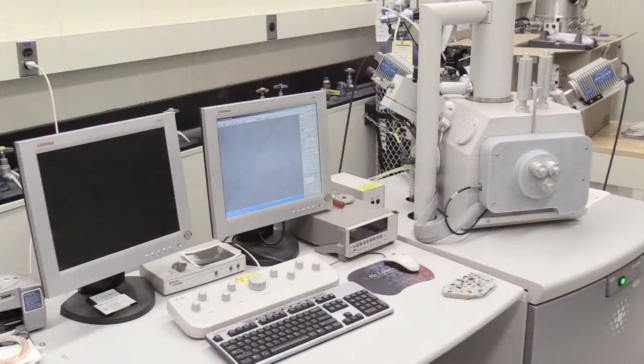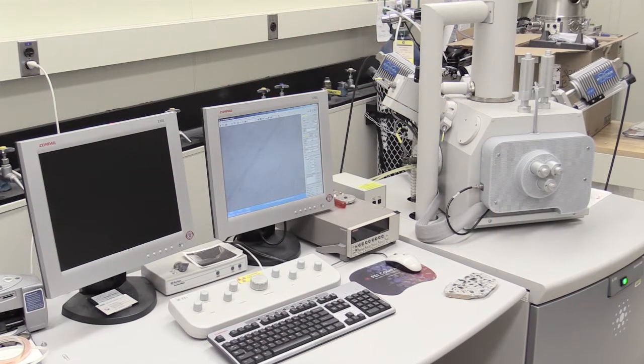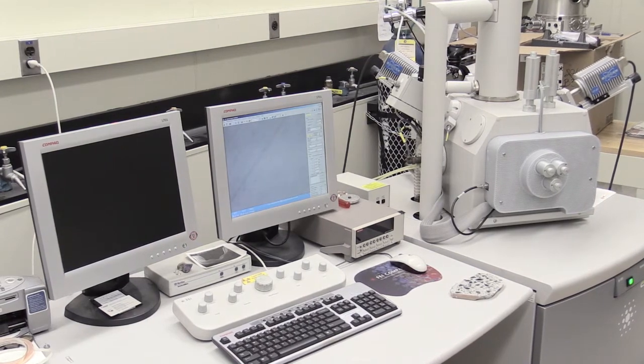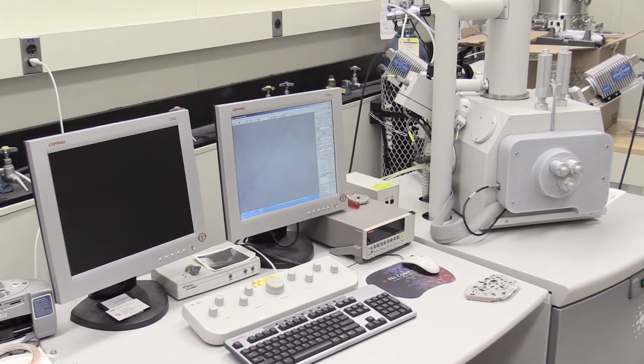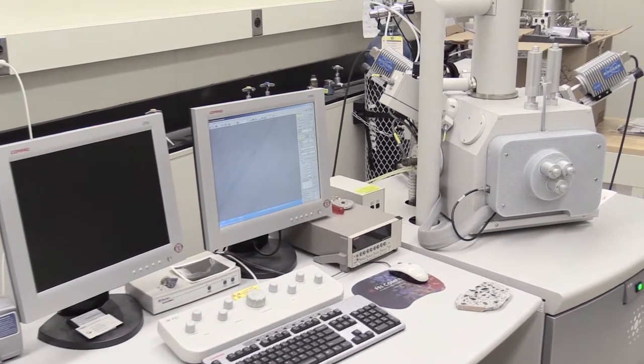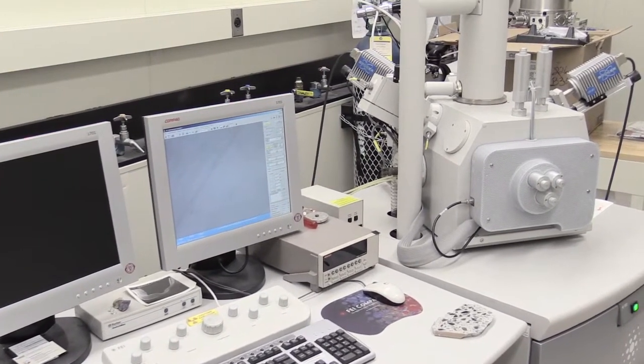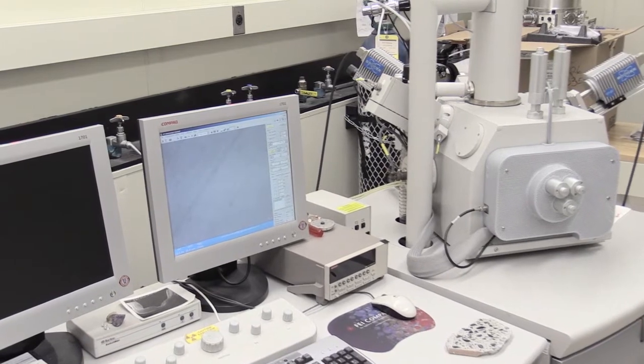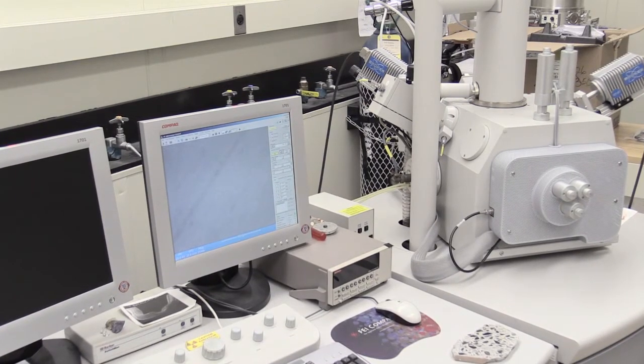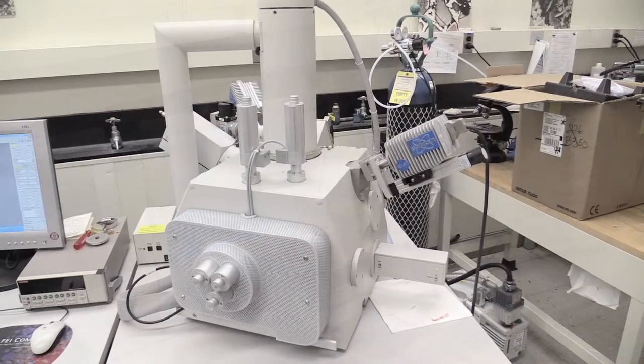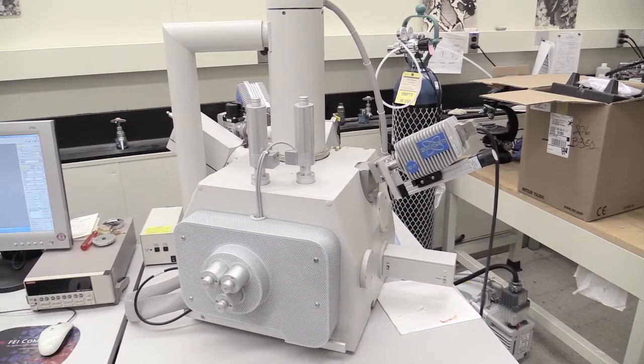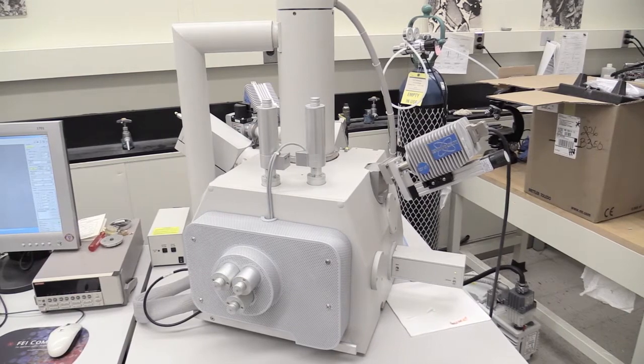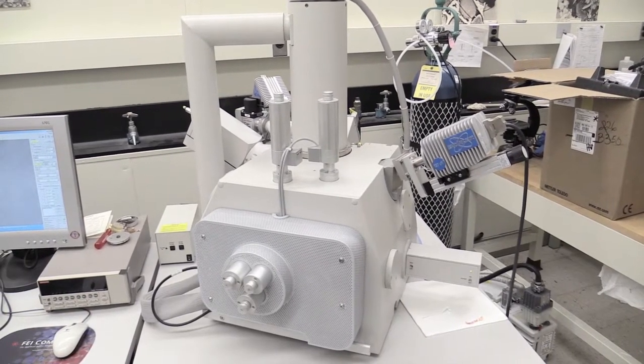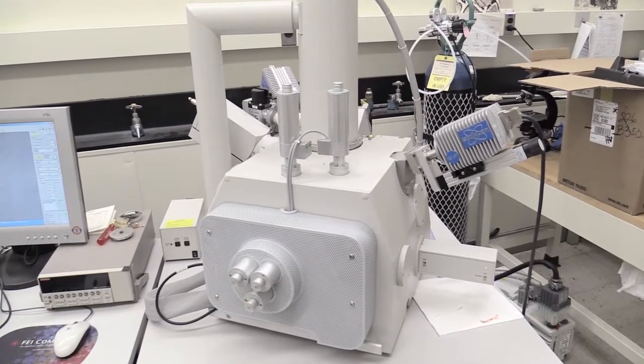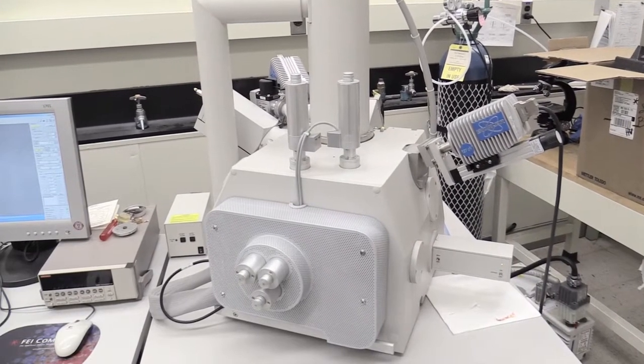The environmental scanning electron microscope has an extra-large chamber to accommodate large specimen imaging. Being an environmental SEM, one can condense water on a specimen to investigate material-water interactions in real time. It also operates in a low vacuum mode, so specimens do not need to be coated for examination. This instrument is coupled with an X-ray microanalysis and imaging workstation and is used for quantitative microscopy and characterization of cement clinker for standard reference materials and cementitious materials for our hydration modeling.